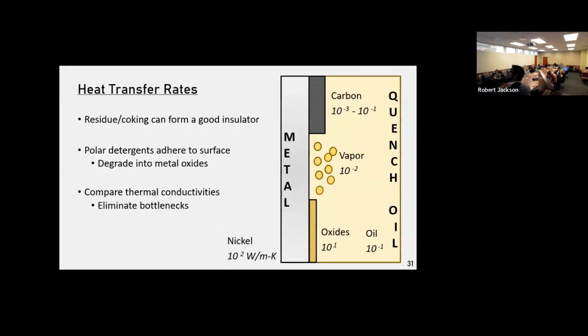Something that we look at on the surface level, the surface science, is you have to think of the thermal conductivity. So if you think initially it's very easy, you just stick this hot piece of metal into oil or water, and then it just gives off all this heat. But there's a lot of surface chemistry involved. So if we've got this hot metal surface and the quench oil is kind of stealing the heat away, what's going to happen is that quench oil is going to pyrolyze. It's going to turn into carbon deposits, and those can be insulating. We can have the petroleum oil spontaneously flash vaporize, and it's forming a gas or vapor barrier. And then we can have inorganic components of the quench oil decompose into oxides, which tends to be most favorable.